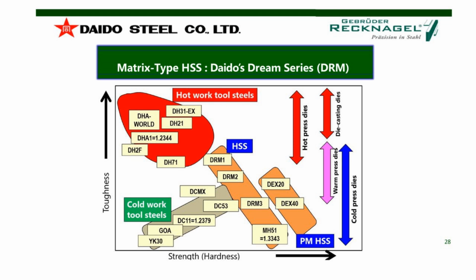The Dream 2 works with a maximum hardness of 62, also up to 63 HRC, but the toughness is higher than with DCMX, and the Dream 1 is a little bit special. It's not a typical HSS steel. You can see the positioning is very close to the hot work tool steels. That means the hardness is limited up to 56 to 58 HRC, but the toughness of Dream 1 is extraordinary. It's the typical toughness of a hot work tool steel. That means Dream 1 is a mix between HSS and hot work tool steel, and it's very special.